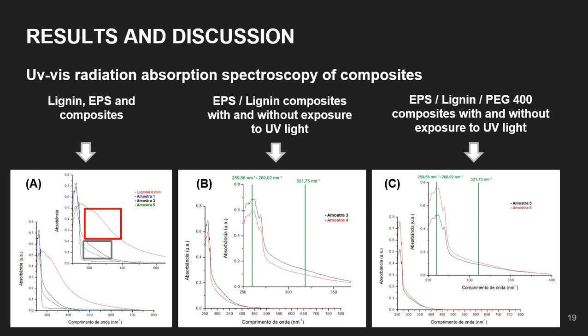Figures B and C show the results of the photochemical treatment effect. This apparently has no influence with respect to the wavelength range of the composites. What could be said would be the variation in the intensity of absorption, but due to the limitations with respect to gravimetric measurement in the laboratory, as well as the sensitivity of the technique, this could be caused maybe by a variation in concentration in the preparation of the samples for analysis.